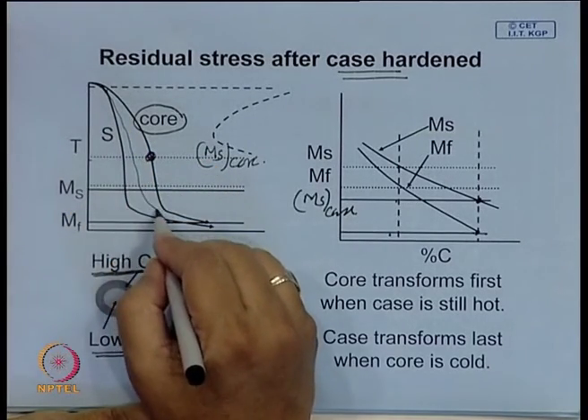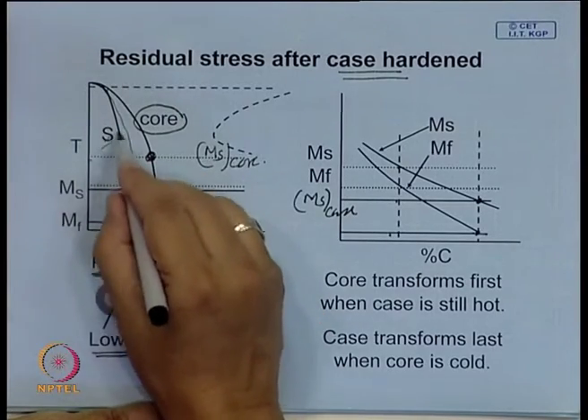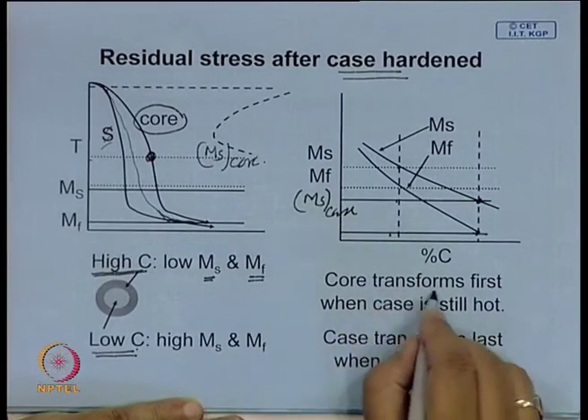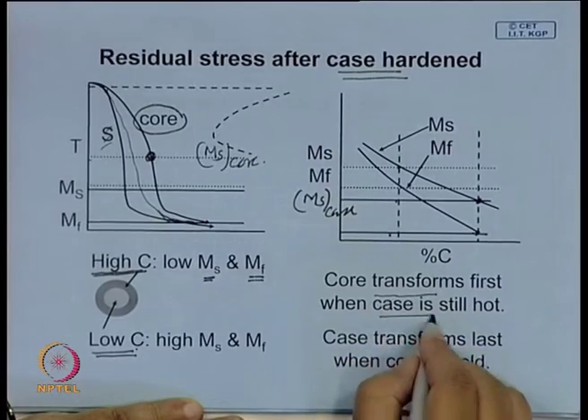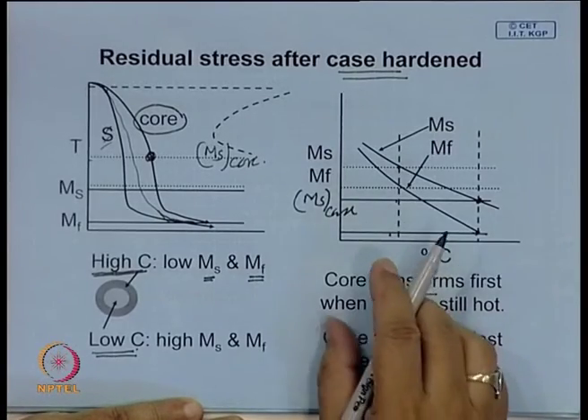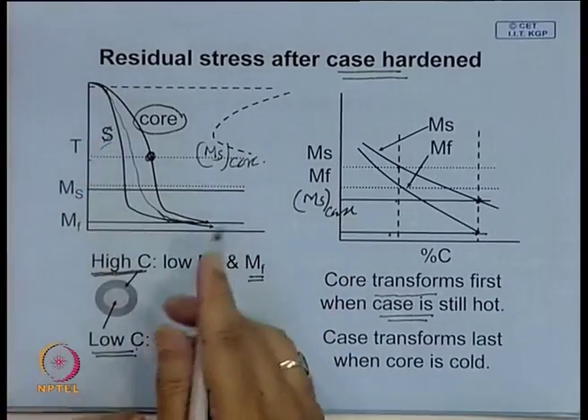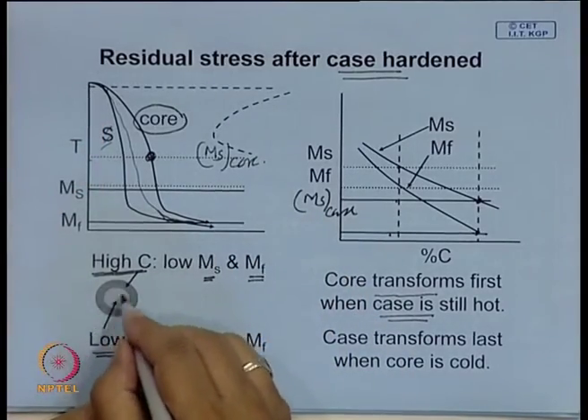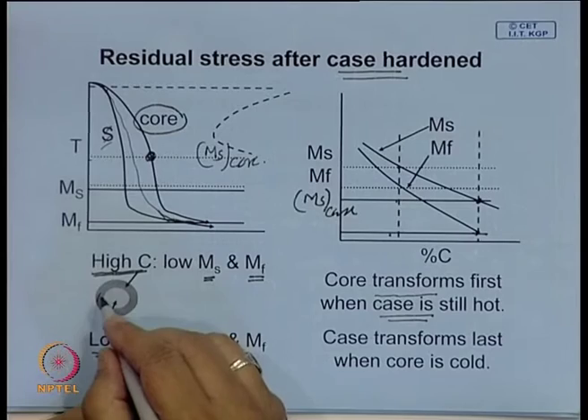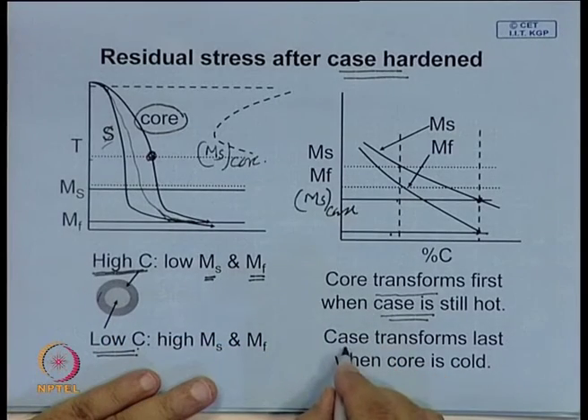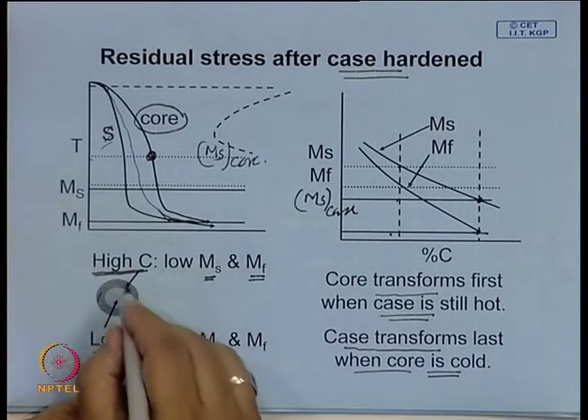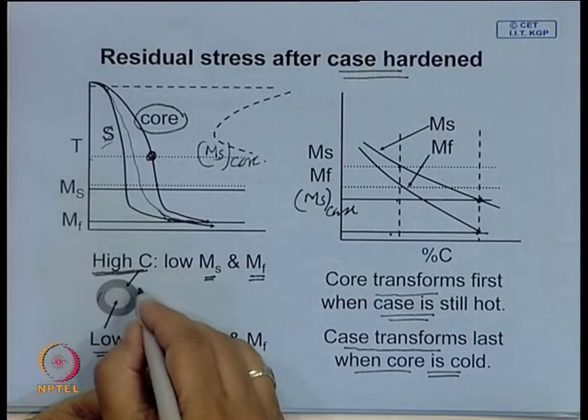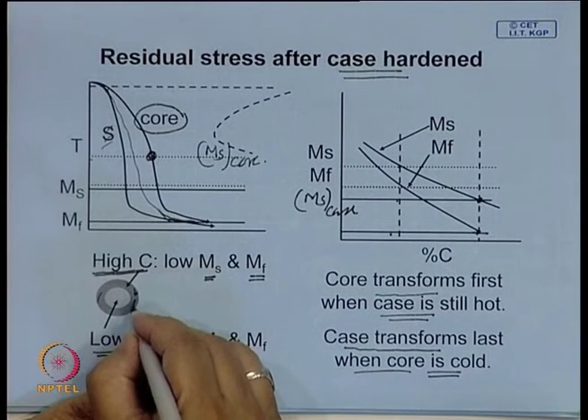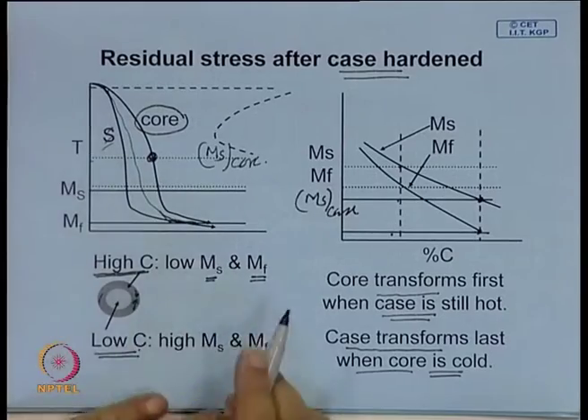So the trick is the core transforms first when the case is still hot. Therefore, when the core tries to expand, that case can deform and accommodate the strain, and later on the case transforms last when the core is cold. So the core will not allow this to expand. Therefore, a residual compressive stress will develop on the surface.